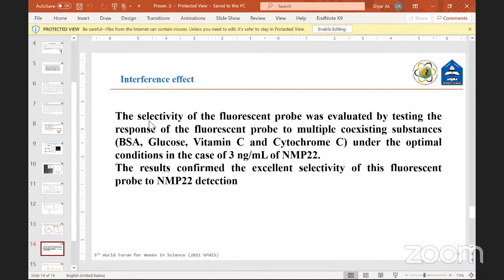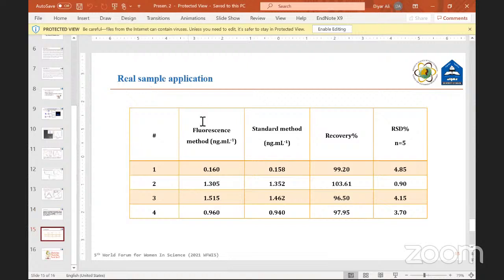For the study of interference, the selectivity of the fluorescence probe that we synthesized was evaluated by testing the response of the probe to multiple coexisting substances, substances that may be present with our target in the urine, because we use urine as a sample for testing. It may contain BSA, glucose, vitamin C, and also cytochrome C. We used these as interferents, and we don't see any interference between them. The result confirmed the excellent selectivity of our probe.